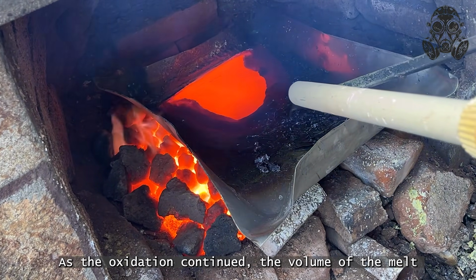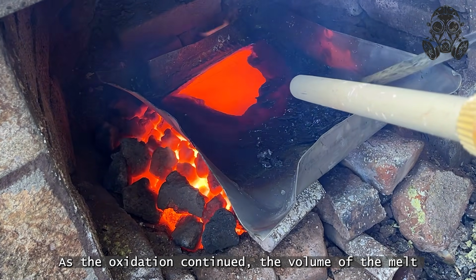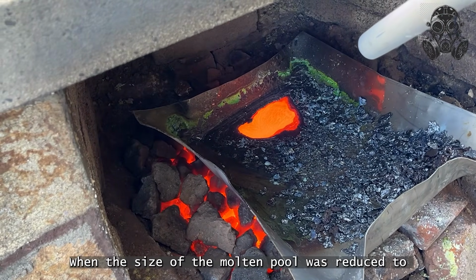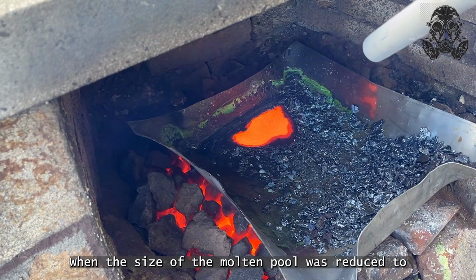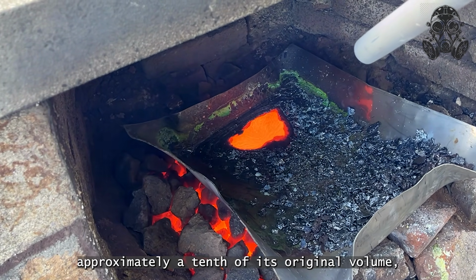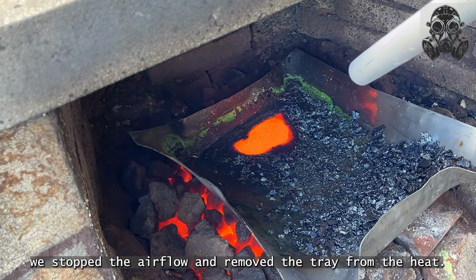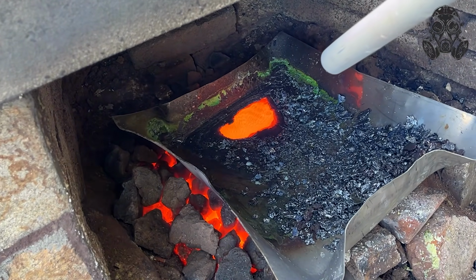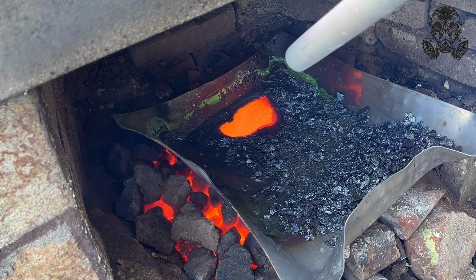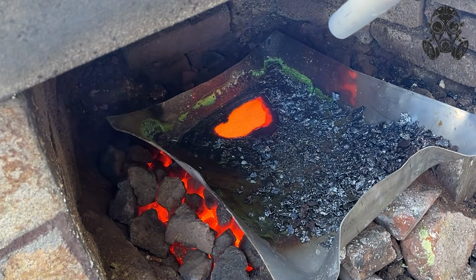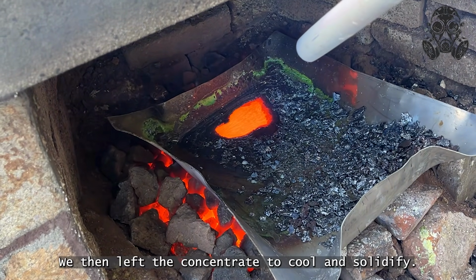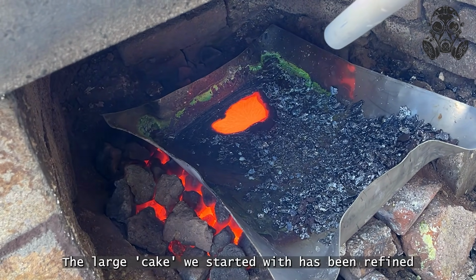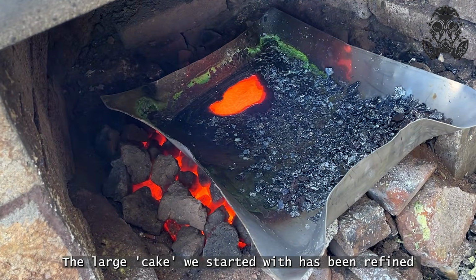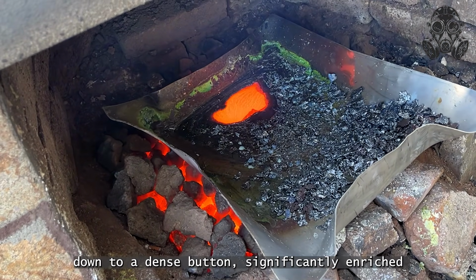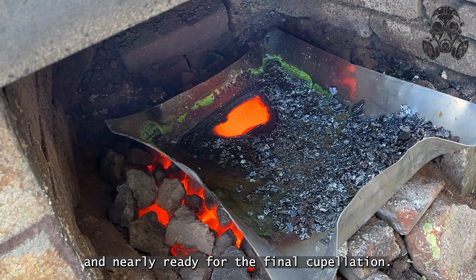As the oxidation continued, the volume of the melt steadily decreased. When the size of the molten pool was reduced to approximately 1/10 of its original volume, we stopped the airflow and removed the tray from the heat. We then left the concentrate to cool and solidify. The large cake we started with has been refined down to a dense button, significantly enriched and nearly ready for the final cupellation.